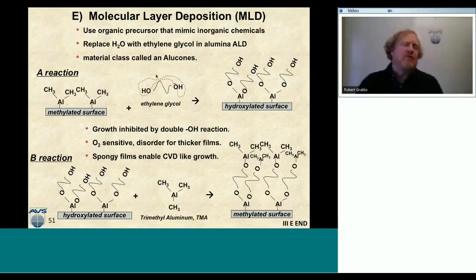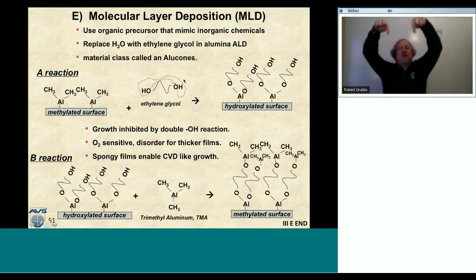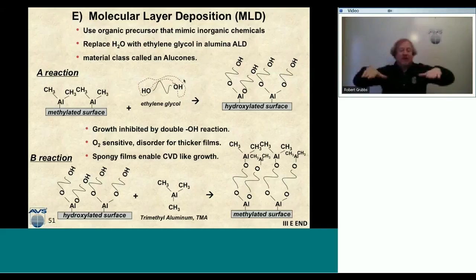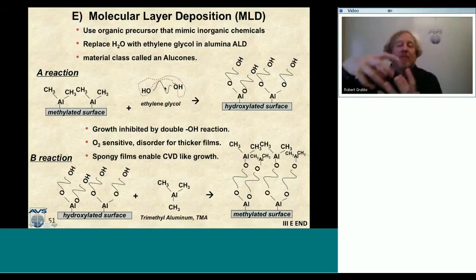But there are a couple of problems with this MLD. One, you can see that I have two OHs on this group. So there's nothing to stop this molecule from coming down with both OHs, reacting with those methyl aluminum bonds, and then the surface would terminate; it wouldn't react anymore. The surface reaction would shut off. So that's no good. It's probably better to build organic molecules that have these groups a little further apart.